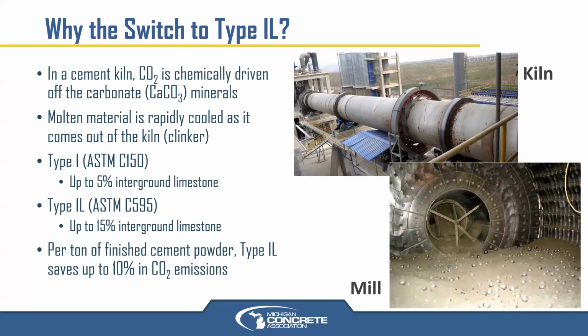So they collect that clinker and then they grind that up into a powder in a mill. The raw ingredient to the mill is now the clinker plus some other things, gypsum to help control the set, and maybe some other fillers, such as raw limestone that didn't go through the kiln. And then those steel balls, you can see them in that picture, bounce around as that mill is turning at a high rate of speed, and those very high strength steel balls bash all those ingredients and grind them down into a powder.